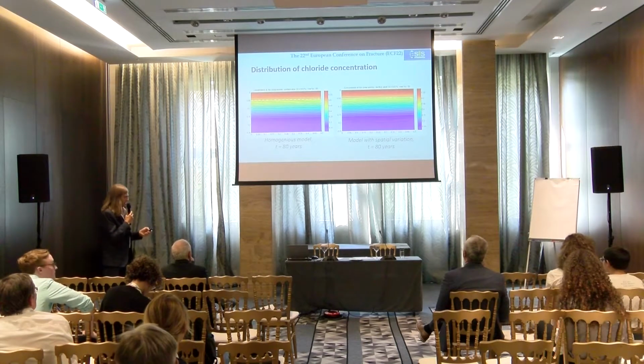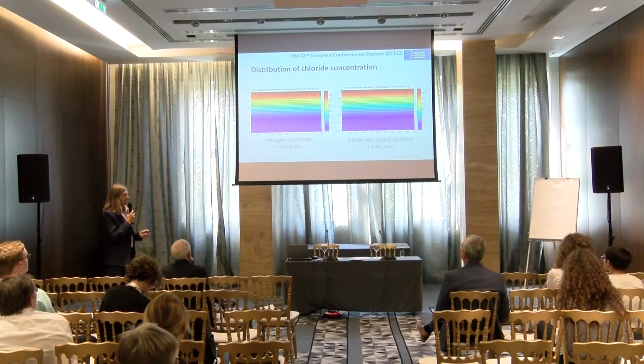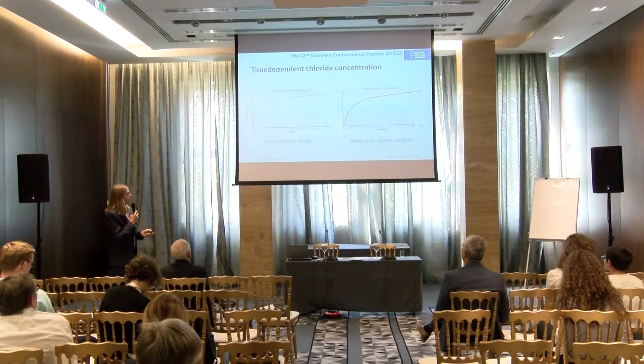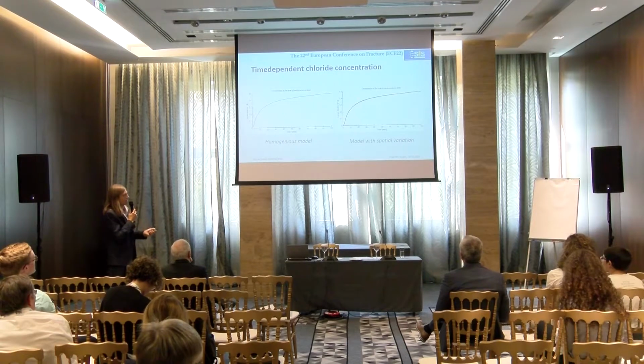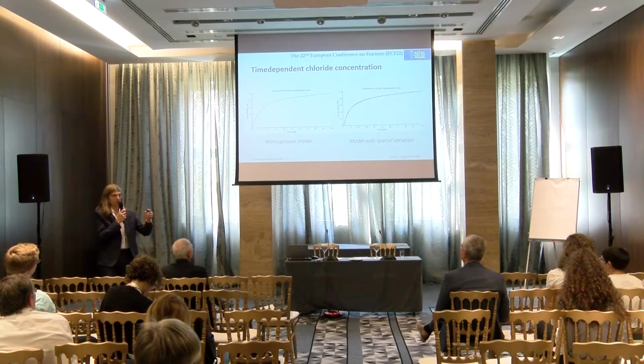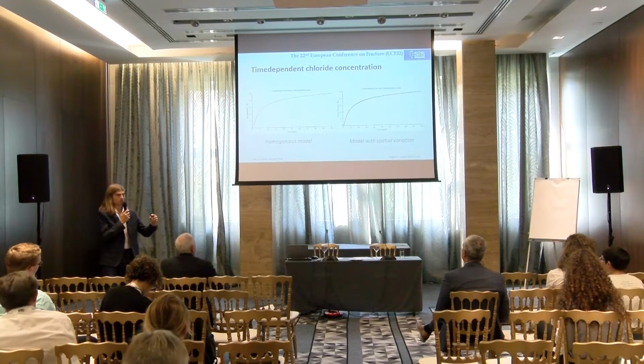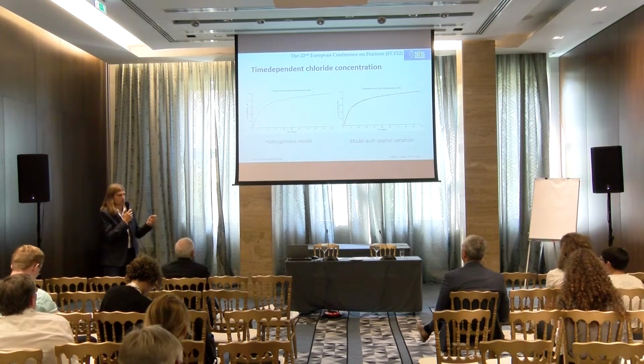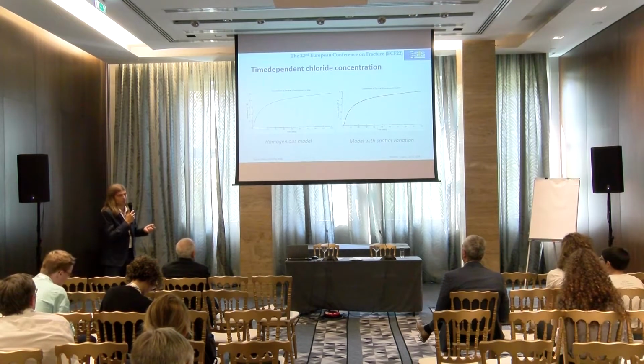But if we go back to the initial picture, here we cannot go to mesoscale. We cannot model the aggregate effect and the paste effect. So in the current implementation, it is not what we have expected. These are the results of the concentration of chlorides at the level of the reinforcement, the homogeneous approach, and this is the non-homogeneous approach. And these three lines that basically overlap each other are minimum from the simulation, maximum, and the mean value. So we can see that this implementation of spatial variation has basically no significant effect.